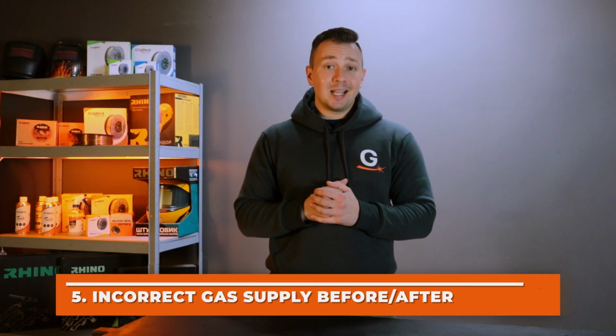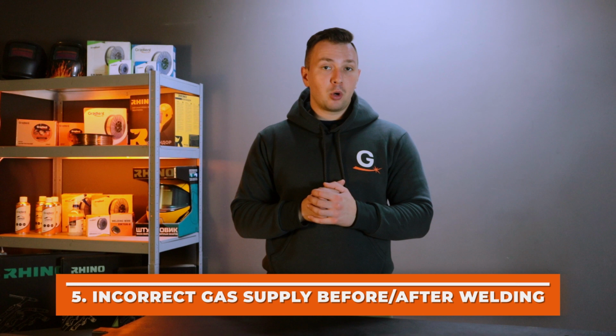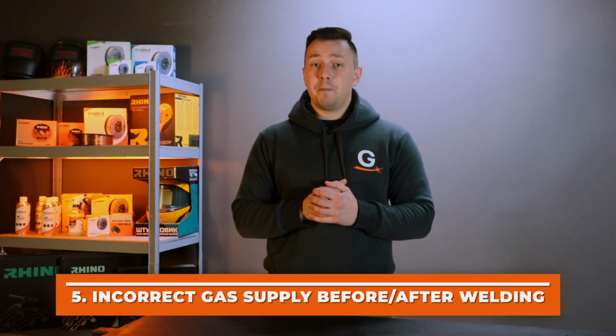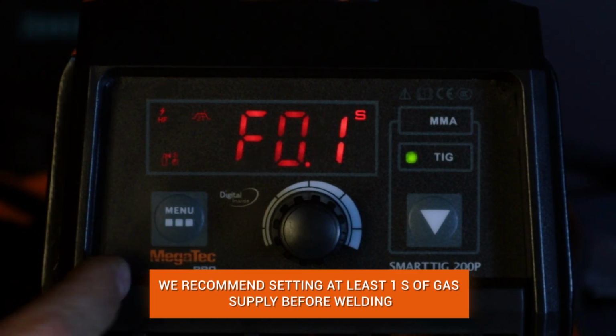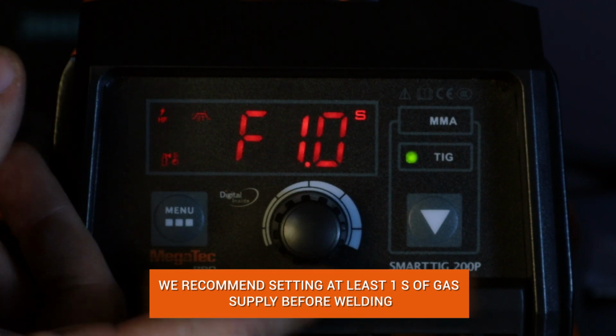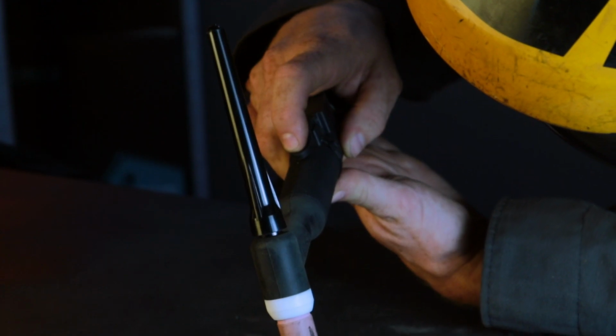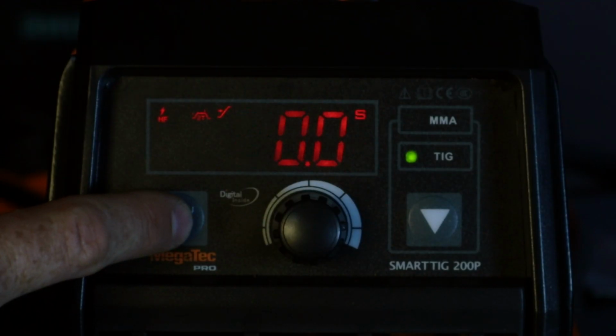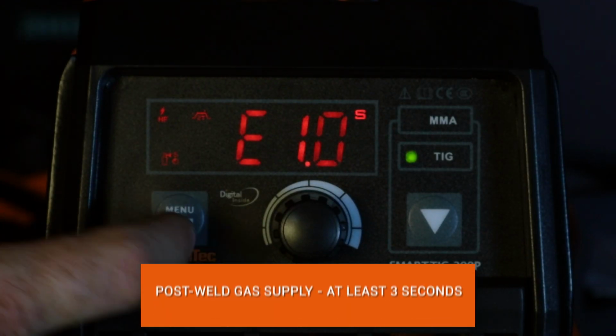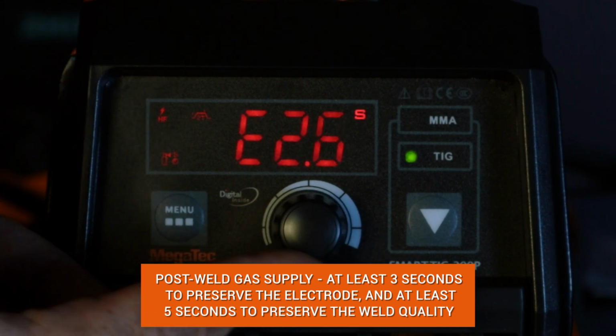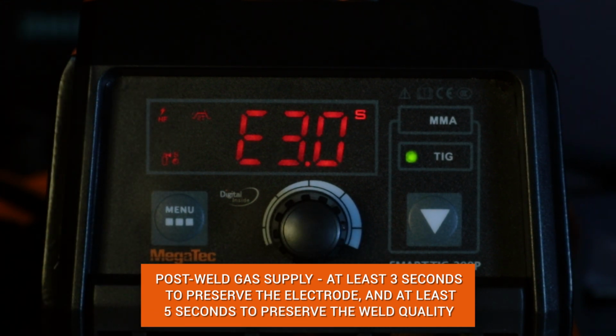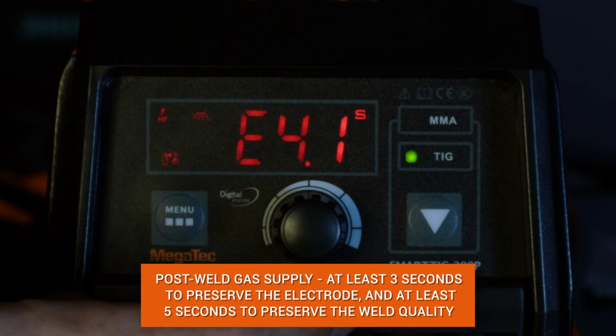The last, fifth mistake. Setting a small gas supply interval before and after arc ignition. We recommend setting a minimum of 1 second of gas supply before welding. This option will allow you to feed the shielding medium and ignite the arc properly. Regarding the gas supply after welding, we recommend setting the gas supply after welding for at least 3 seconds to preserve the tungsten electrode and at least 5 seconds to preserve the weld quality.